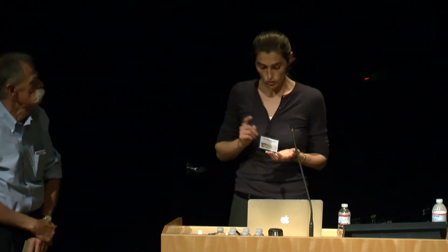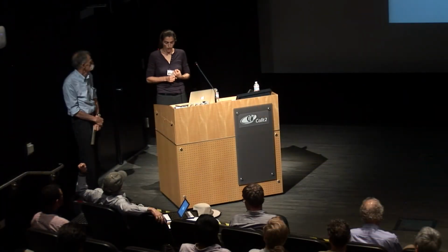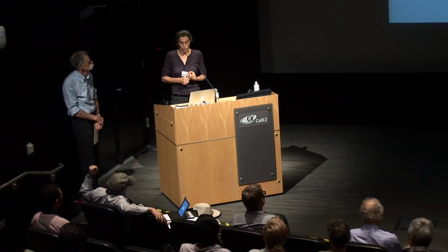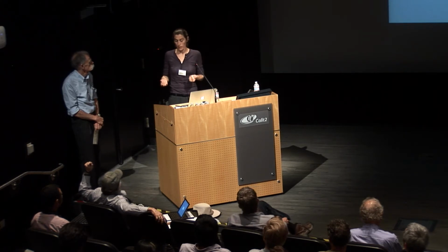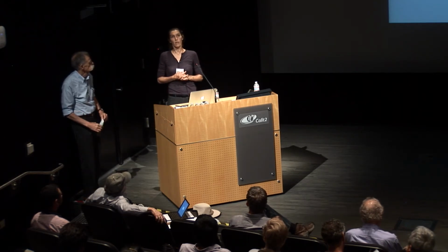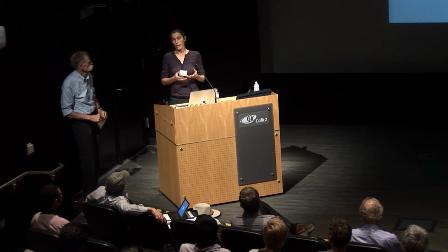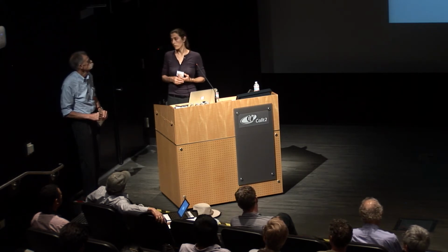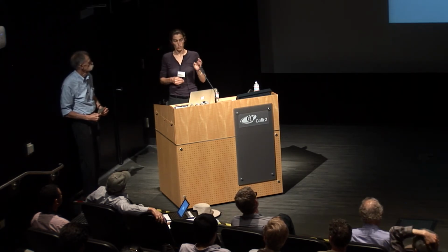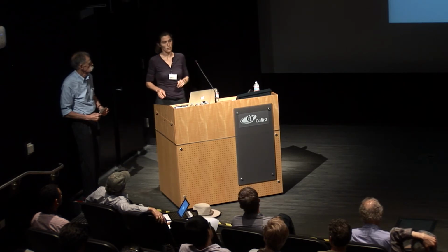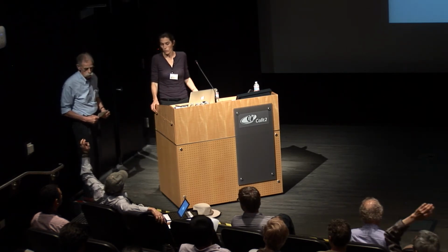You can do implantation with nitrogen. And one can also just start with nitrogen-rich diamond and do electron irradiation to generate vacancies. So one can generate nanodiamonds with, say, 50 nanometer diameter that have hundreds and hundreds of NV centers inside of them. Again, kind of similar to the nanocrystals that Jim was talking about.